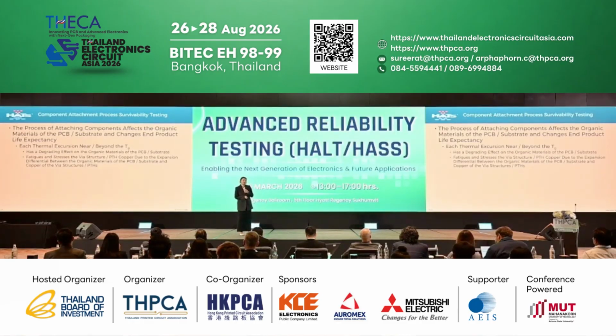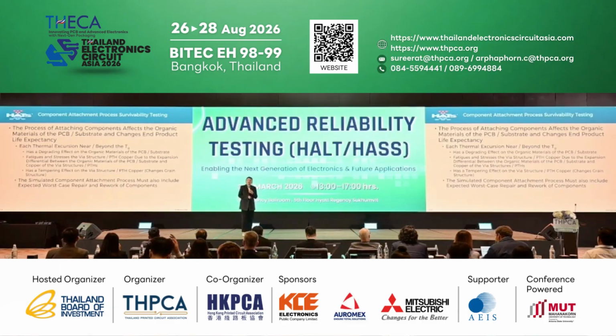The component attachment process survivability testing. When we talk about survivability testing, it is a test because every thermal excursion near or beyond the TG has a degrading effect on the organic material, PCB and the substrate.